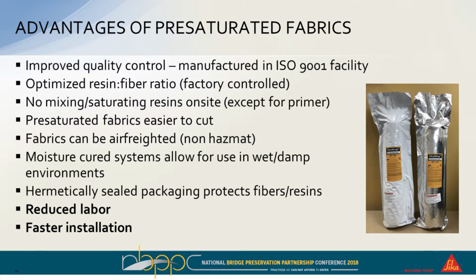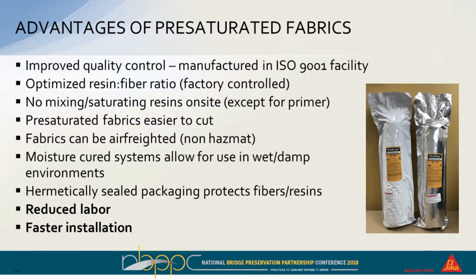They're non-hazmat material. The difference between the B-stage epoxy that I mentioned earlier and the ones that are now used for bridge applications is a different resin type system. So in this case, what we're using is a moisture-cured resin that allows it also for use in wet or damp conditions. In order to prevent it from curing prematurely, it gets packaged and shipped in hermetically sealed pouches or foil packs to keep the moisture out of the package until you open it up. Once you open it up, it gets exposed to the ambient relative humidity, and that's when the curing process will actually start.